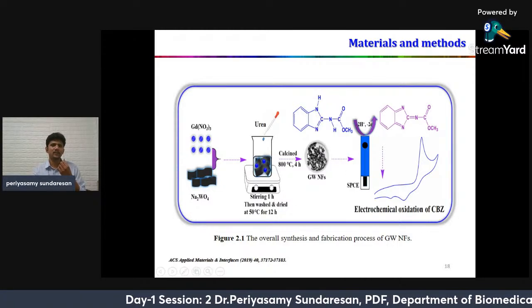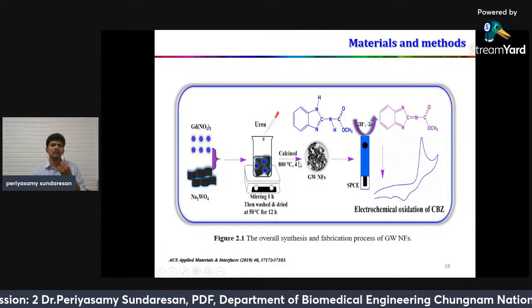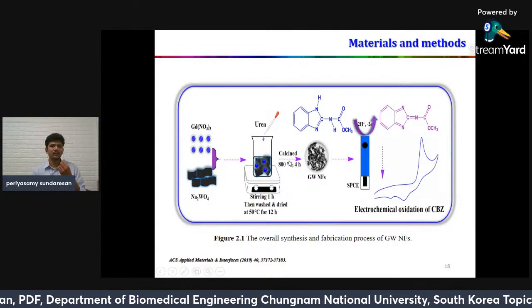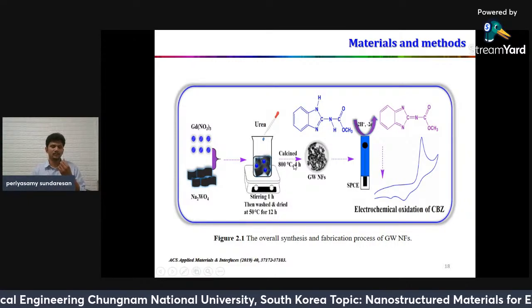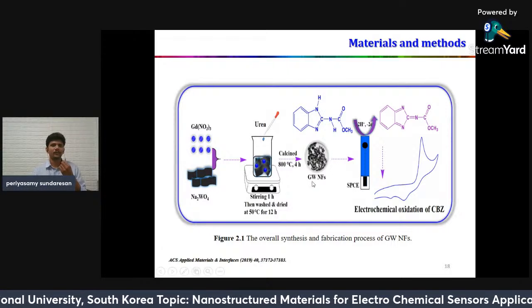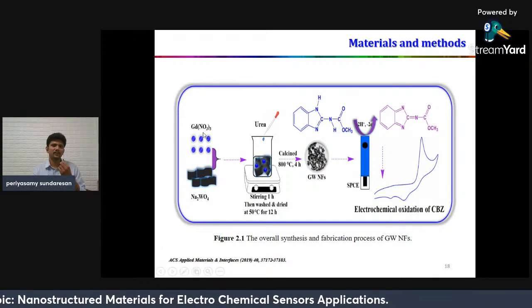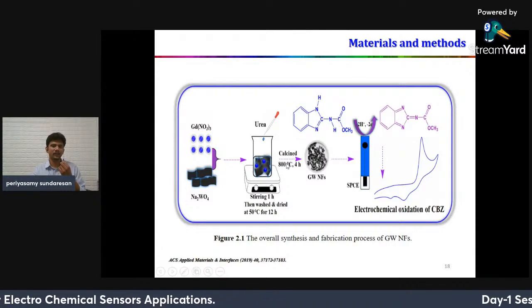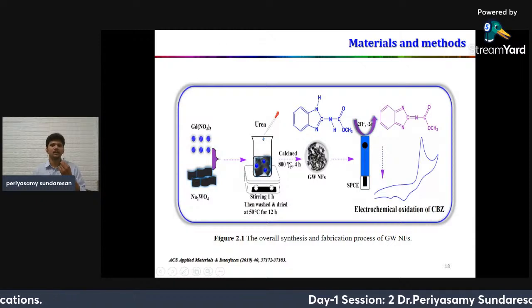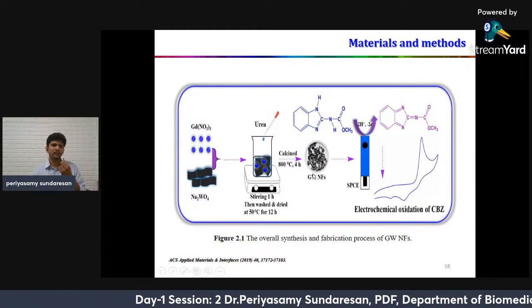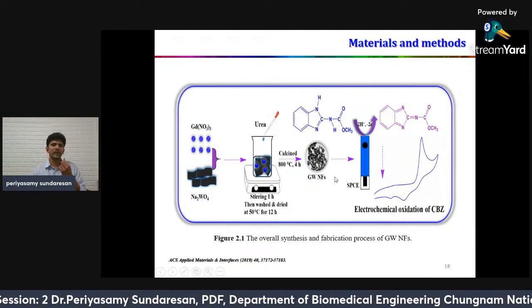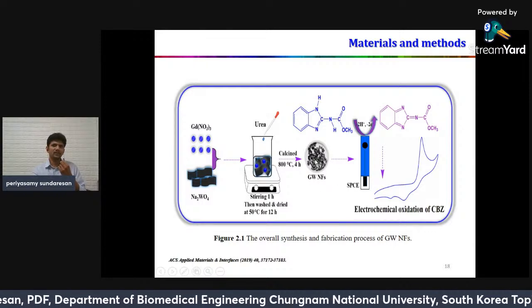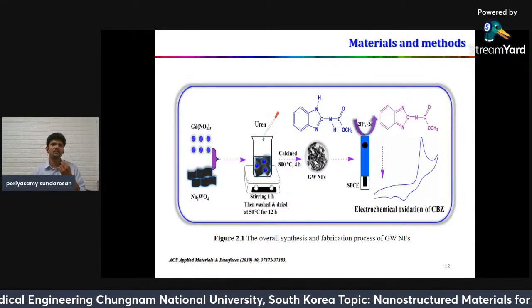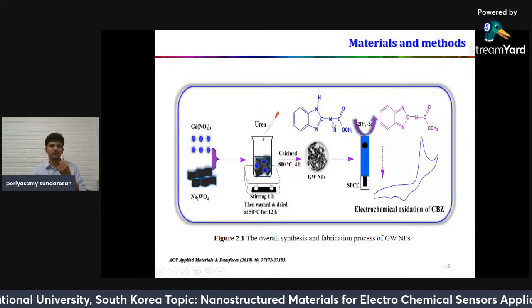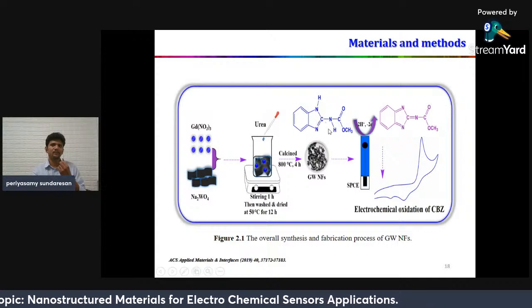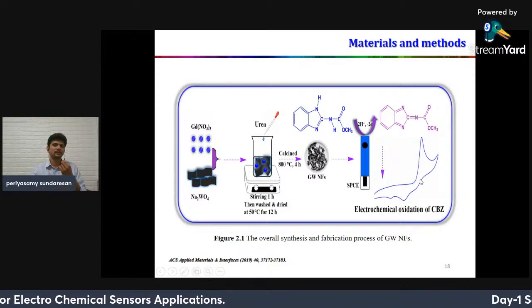Before the product formation, we need calcination, we need annealing for this product, because if we heat at a higher temperature, the crystallinity will increase. Initially this is a macro size substance, but if we heat at a higher temperature, the size will decrease. We get a two-dimensional structure. I expected a three-dimensional structure, but unfortunately I got only a two-dimensional structure. The prepared structure will be confirmed with various characterizations, and the catalyst will be applied for electrochemical sensors like carbendazim detection. I get a signal from the CHI instrument.